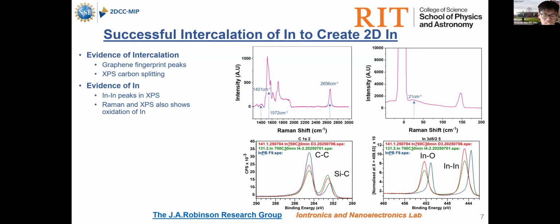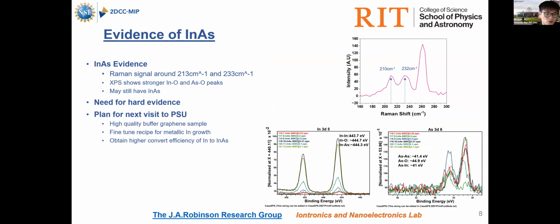And then our hypothesis at this step is that even though it has some kind of oxidation of the indium, during the arsenic growth process it might still be able to convert into indium arsenide, metallic indium arsenide, during the high temperature growth process. Therefore, we took the sample back to RIT and used it in the MOCVD chamber for the arsenic integration. The good news is we do see some evidence of the indium arsenide from our Raman data, which is shown